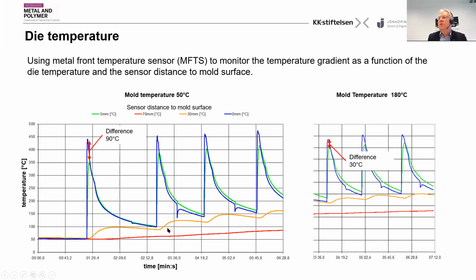And then we go 30 millimeters. You can see only down here that the die is getting hotter and hotter. So you can control: are you in steady state? Do we have some problems with too high die temperatures and stuff like this? But again, until now, not a lot of people are using it. And I don't really understand why.